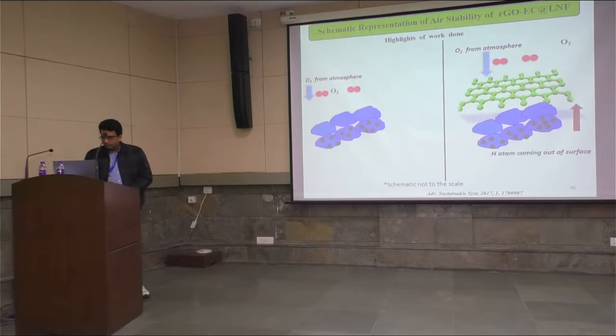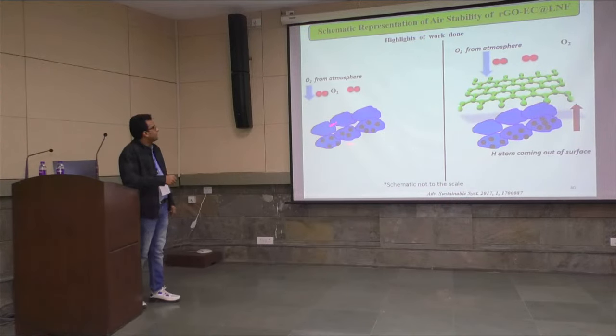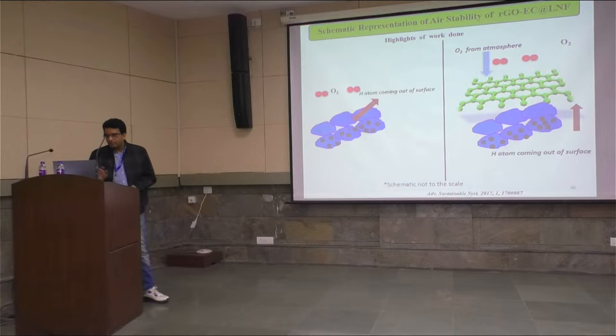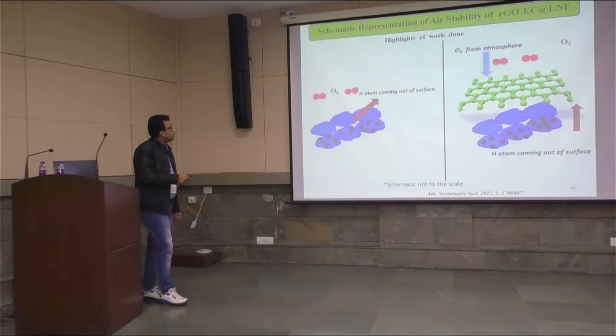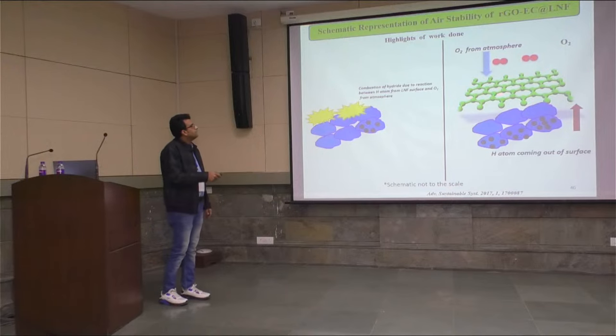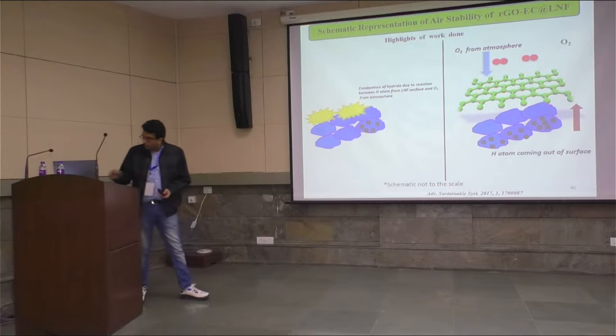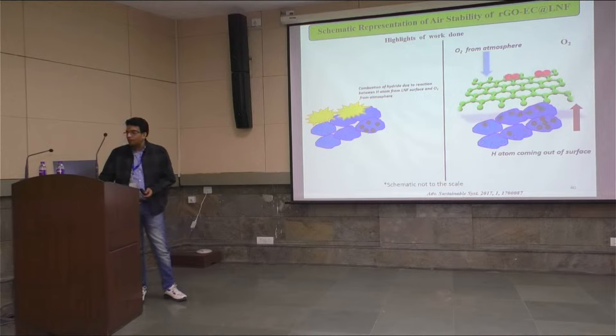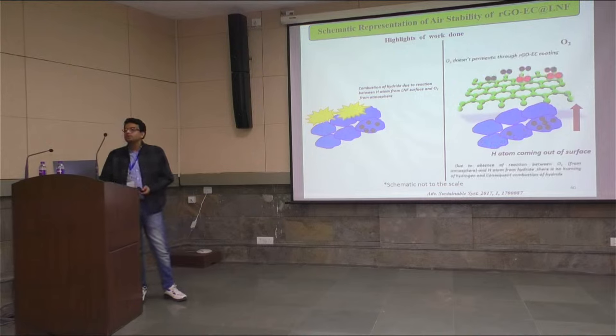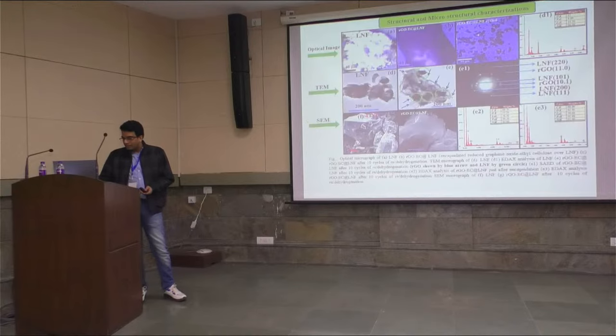Now what exactly happened is that, you can see, this is the hydride, these are the hydride surface and these are the hydrogen. When these hydrogen atoms come at the surface, the oxygen molecule reacts with the hydride hydrogen at the surface and the material catches fire. But if you have a graphene cover, then this graphene cover will not allow oxygen to come to the hydrogen atom. And before that, hydrogen atoms become hydrogen molecule, and when hydrogen molecule reacts with oxygen, then the reaction is not so heat releasing that the hydride catches fire.